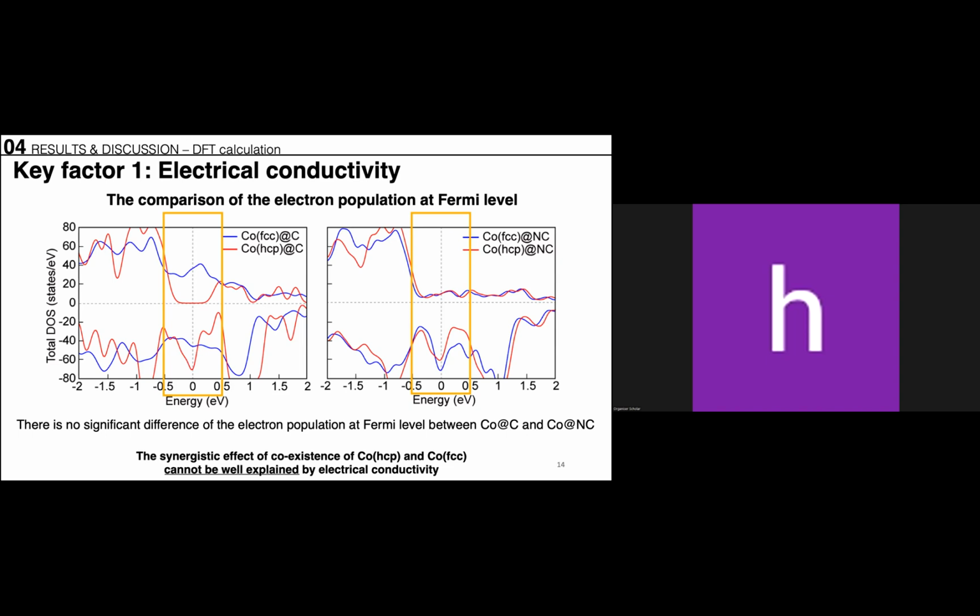In this work, the interface was stabilized even during the reactions. One sample is made only of FCC, one only of HCP, and the other is a mixed phase. But the mixed phase was the best one, because HCP gives good surface reaction kinetics, but FCC makes a strong electric field to push the proton away, so that the local pH value is kept high for active emission. So they have different phases with different roles.